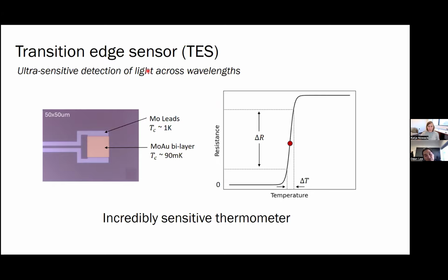I already said this is used in astrophysics. What might provide a little bit of heat to change the temperature is a photon or some radiation falling on your sensor. So how does this kind of device look? This color of purple is essentially the substrate. Then you have a superconducting lead to this device. In this case, it's made out of molybdenum, which has the superconducting transition at about 1 Kelvin. And then there's a weaker superconductor sandwiched in between the leads. In this case, it's a molybdenum gold bilayer, and that has a much lower critical temperature. So it's a superconductor structure.